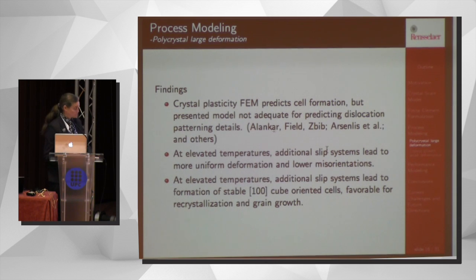So just summarizing that section. Crystal plasticity finite element modeling predicts to a certain degree cell formation, but the present model is not adequate for predicting dislocation patterning details. There's been other work, I think very nice work, by David Field and Mohammed Zabib at Washington State and Arsenlis et al., who look at the individual dislocation types and are able to predict dislocation patterning by the details of those interactions, which we've kind of homogenized out in the formulation that I presented.